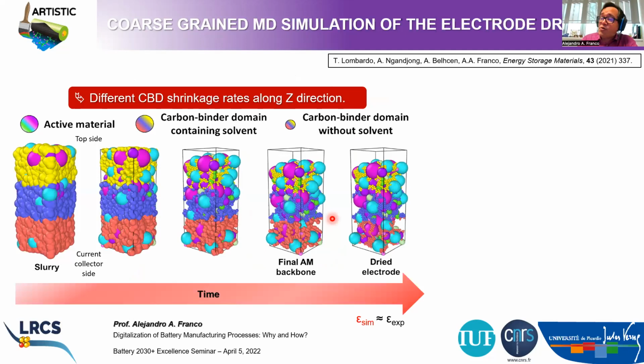The model is also able to capture the impact of the drying rate on the microstructure, and in particular on the phenomenon called CBD migration, or carbon binder migration. And here you see how this works. Basically in the model, we imagine that the CBD will shrink at different rates depending on the depth of the slurry. So if you are on the current collector side, the CBD will shrink at a rate much slower than the one that is on the top. And in that way, we are able to predict electrode structures that will be heterogeneous along the electrode thickness in terms of CBD volume fraction, right?